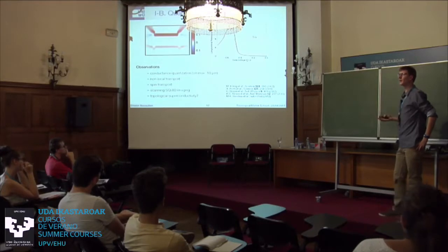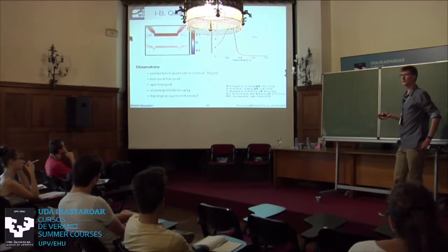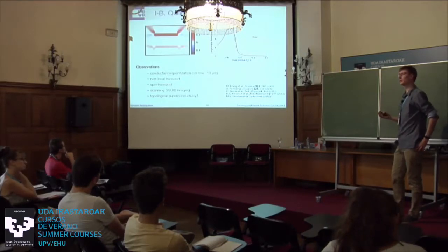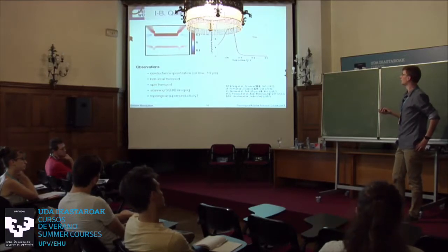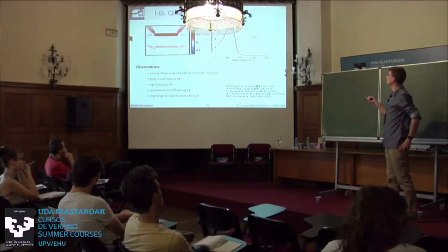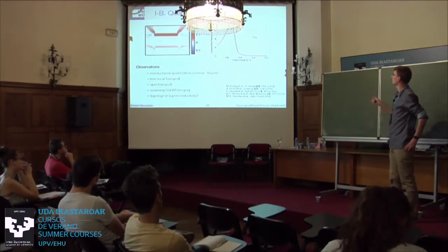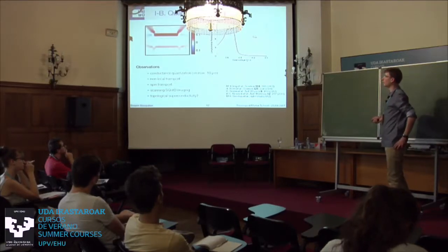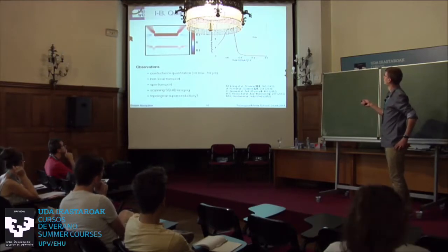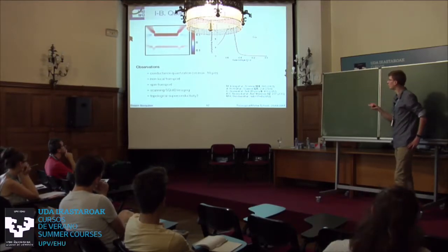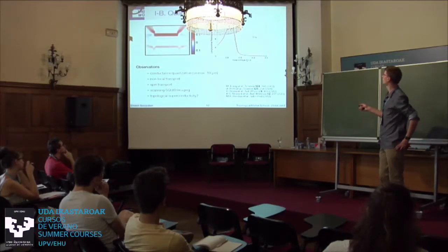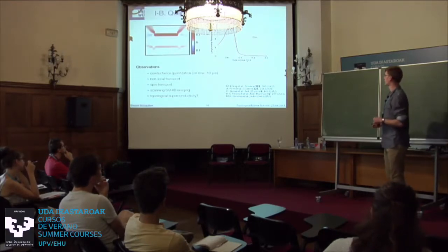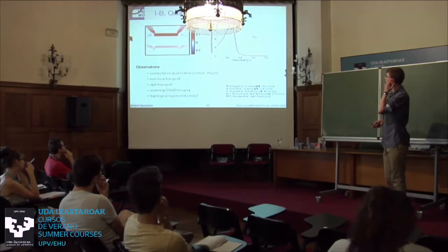This is indeed, I'm not going to hide it, very hard to get good quantization in these quantum wells. Nevertheless, recently the lithography has been massively improved and keeps the crystal quality even in very small structures, such that recently we've been able to see quantization that now looks much better than the ones from the past. It's not a log scale anymore, it's a linear scale, and it's more or less reaching the plateau. So this is a good sample. Not all of them are like this. Sometimes they are a bit here, sometimes they are a bit there. We're still trying to fine-tune those structures and understand what limits the quality of these structures.